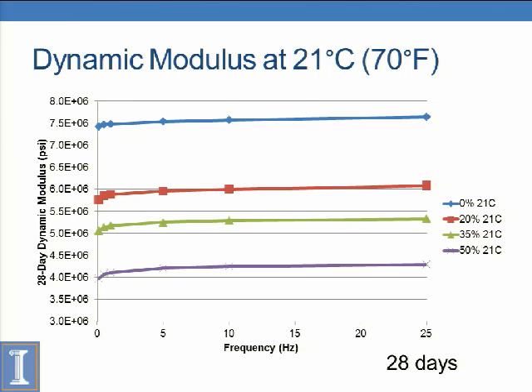That's a good question. Yeah, you probably will have a lot higher deflection in the mix. You'd mentioned temperature dependency. We did not find a temperature dependency in the modulus values. So we tested at 4, 21, and 54 Celsius. I believe the difference in modulus between 4 and 54 was only 7% difference in modulus. So really it was not a big difference in modulus. And that was for the 50% mix. For the 0% mix, the temperature dependency, I believe, was only a 4% difference in modulus in that temperature range.